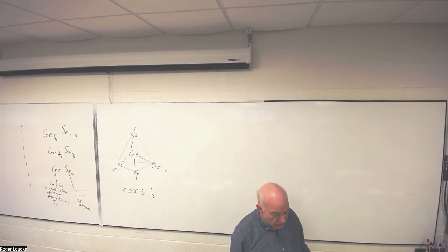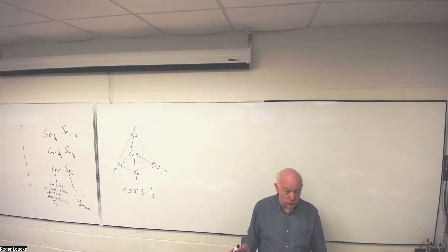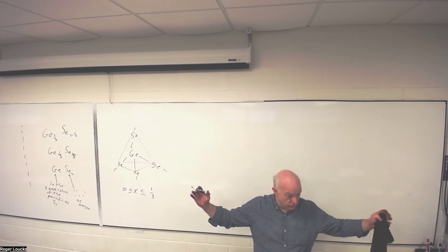And what John actually did his PhD on is coming up with good chalcogenide potentials. It turns out that if you use good chalcogenide potentials, you actually recover the experimental results. It turns out that pure selenium glass makes very long chains.